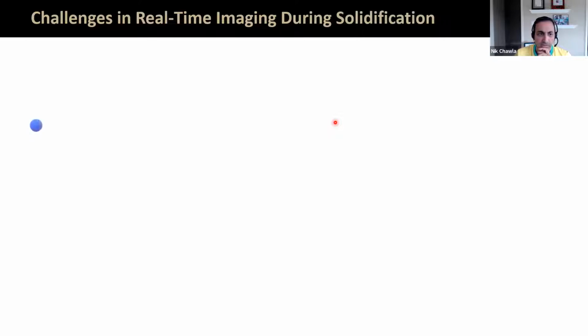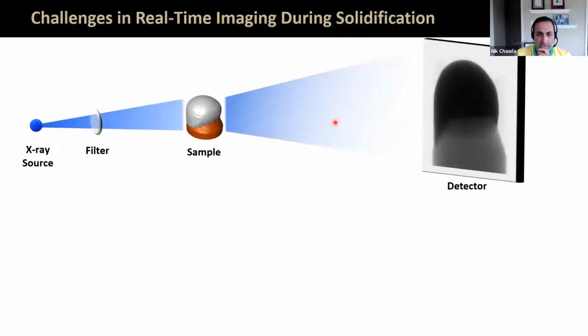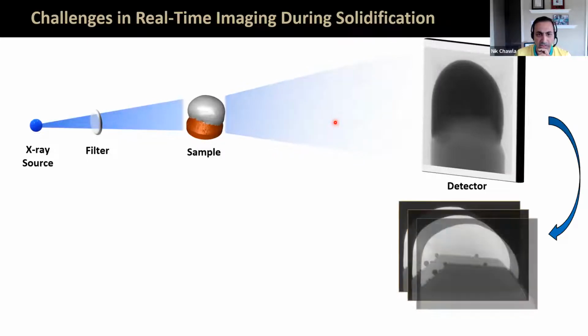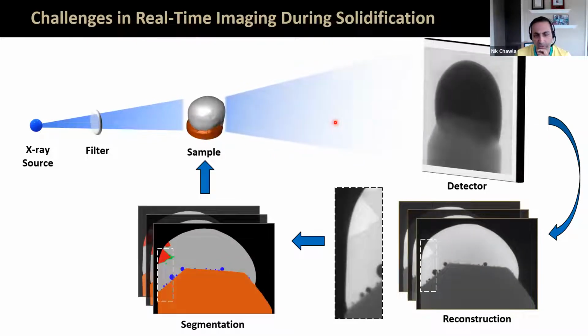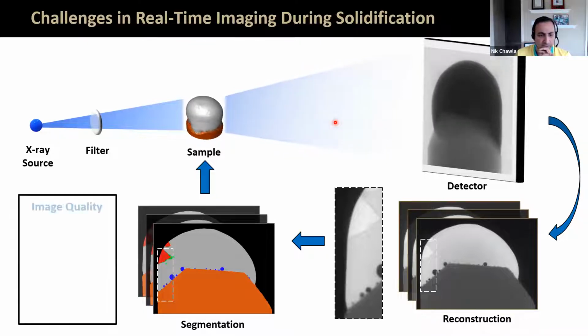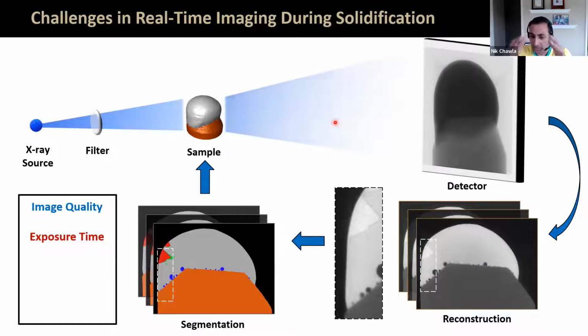So I talked about how the tomography works, but there are certainly challenges in real-time imaging, particularly related to solidification. One of them is the image quality. The longer scan times give you better image quality. But longer exposure times also means that the experiment is going to be longer. And a lot of these mechanisms that are taking place during solidification, nucleation of particles and things like that, take place very quickly. So we want to have very good image quality, but we also want to reduce the